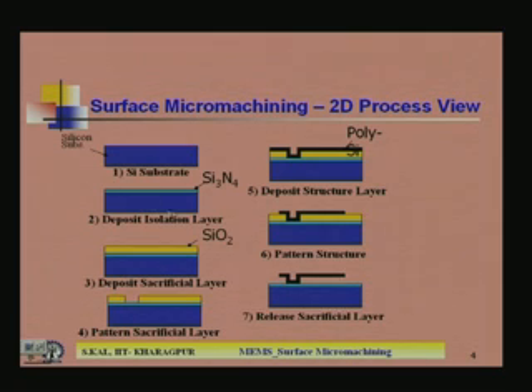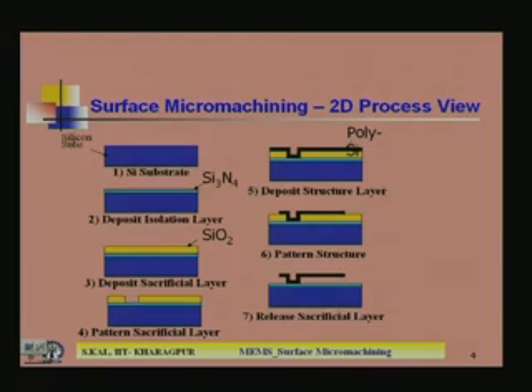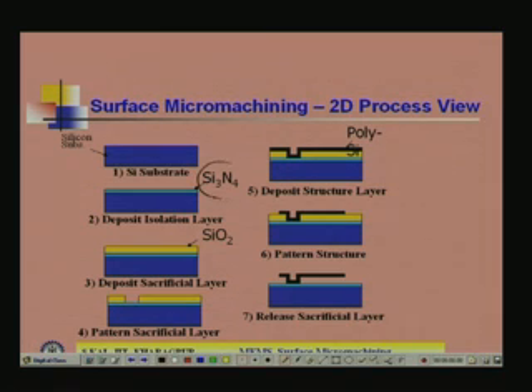Then you deposit silicon nitride, because in many cases the structural layer may rest not on silicon but on some insulating layer. In the earlier diagram which I showed, it is resting on silicon, and silicon is not an insulating layer, it is a semiconducting material. So the hanging structure you are making will have some semiconductor to polysilicon contact. If you do not want that, if you want an isolated free structure, then we have to fabricate it on some insulating layer. That is the reason why in this diagram, first on silicon we have deposited silicon nitride. You can see here this greenish color, that is silicon nitride.